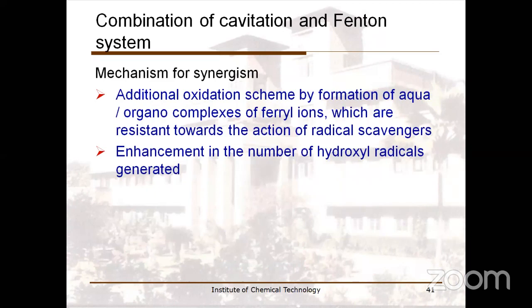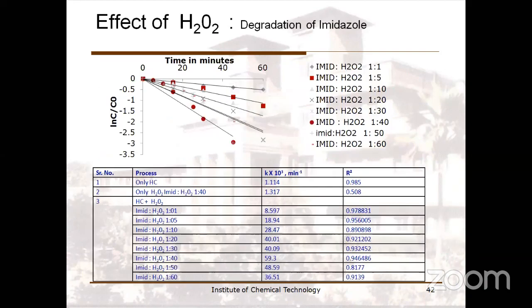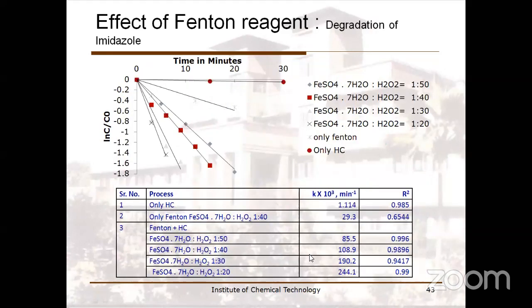You can also use cavitation with Fenton. The mechanism for synergism will be additional oxidation based on formation of complexes, and enhancement in hydroxyl radicals. And here again, some of the rate constants are given for imidazole degradation. And clearly you can see that only hydrodynamic cavitation is giving you much lower values. But if you are combining it, it increases to about 36, 40, and then in the presence of Fenton, about 244 times. So definitely there is a significant increase in the extent of treatment.